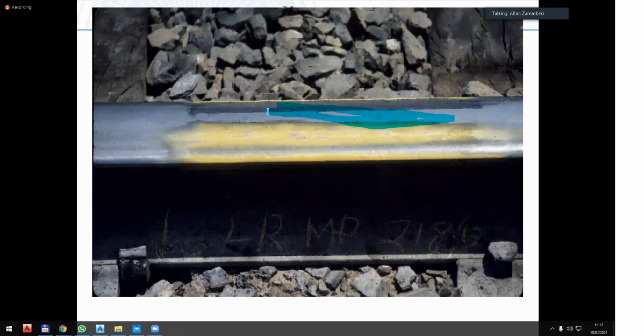This is contact on the field side of the rail. So this is my gauge side. This is my field side. And this is, by the way, one of my field tricks. I like to use a can of spray paint. Spray paint the rail before a wheel goes by, let a train go by, and see where the wheel is. You can see here that most of the wheel contact was here on the field side, which means I have this situation. I have this contact between the field side of my wheel and the field side of my rail, which was the third case I gave you, which is a high overturning moment, a low overturning resistance.